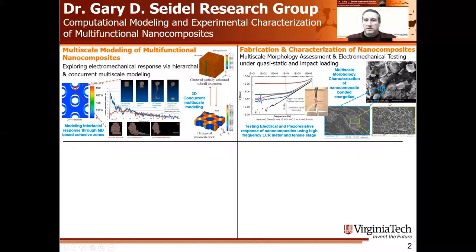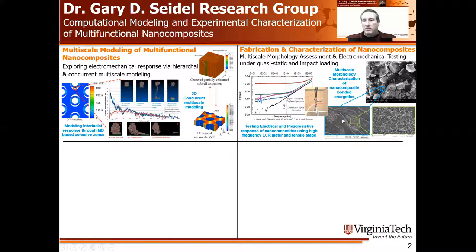In this example, we have an energetic surrogate material. You see particulate crystals here, and dispersed between those particular crystals are carbon nanotubes. Carbon nanotubes are the key technology that we work with, because we want to get a piezo-resistive response or strain sensing response out of our composite.